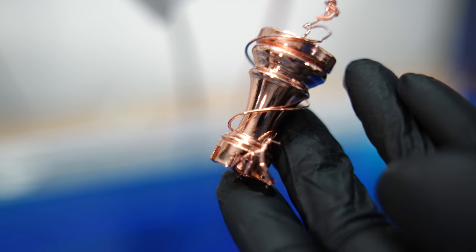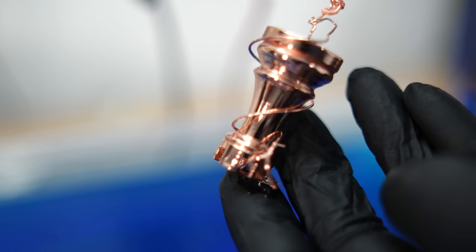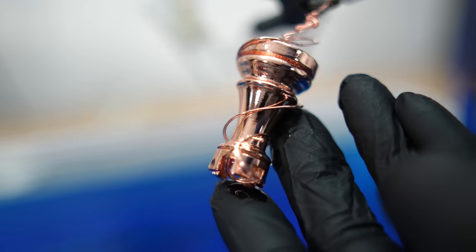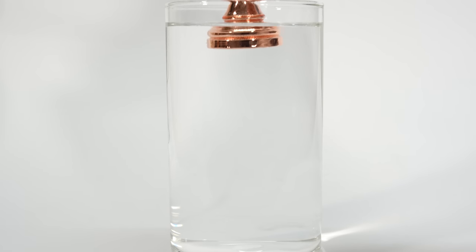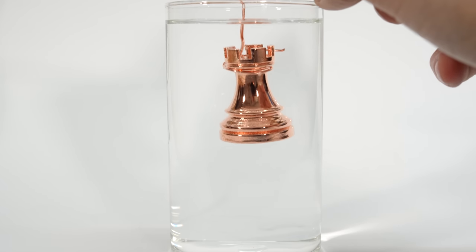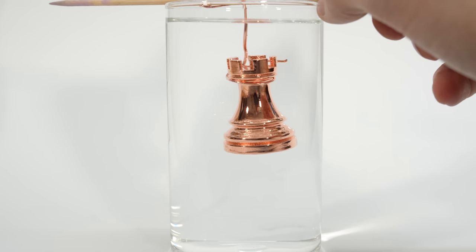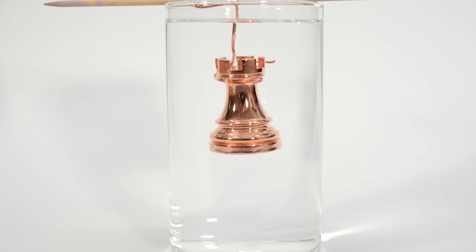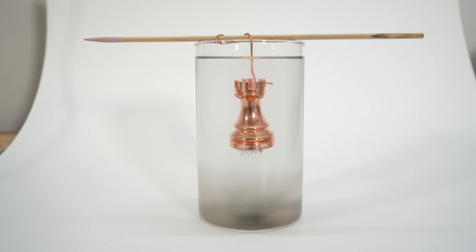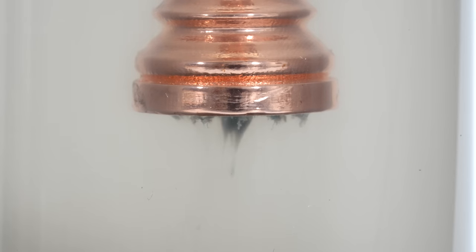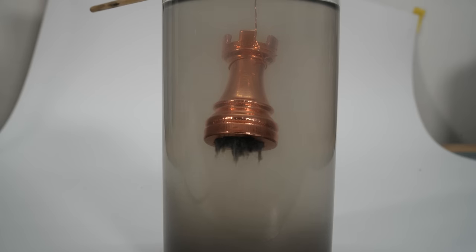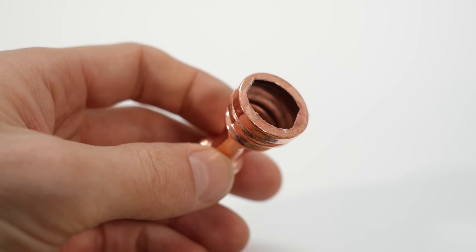A very nice result. Quickly rinse it and then we will dissolve the PVB in a glass filled with 99 percent isopropanol, leaving only the 200 micrometer thick shell. This process takes 24 to 36 hours depending on the thickness of the print.